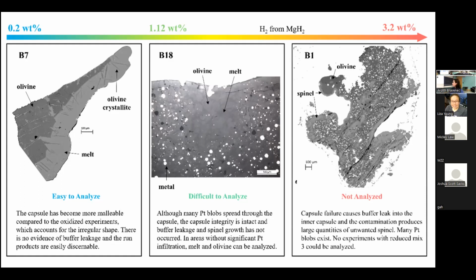And then when we get to 3 weight% of hydrogen in the capsule, things start to get really dire. And this might be expected. You're putting a lot of gas into a capsule and then you're heating it up. The whole thing is going to tend to destabilize, but we're really seeing widespread failure where the buffer, those other metal oxide pairings, are leaking into the capsule, contaminating the system. We no longer have a closed system. And those experiments are no longer very useful.